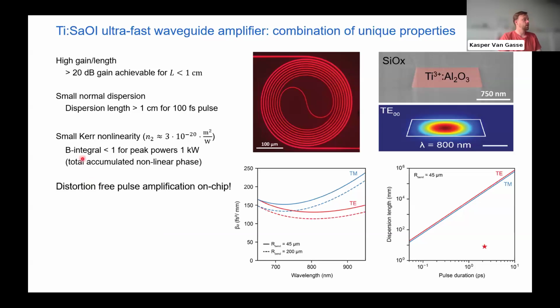On top of that, because of the small Kerr nonlinearity and the fact that it's also short, we have almost no nonlinear spectral broadening or phase accumulation of our pulse. And that's all the way for peak powers up to 1 kilowatt. So you have to imagine it's a very tiny cross-section. You can go all the way to 1 kilowatt. That's starting to be on the order of 100 gigawatt per centimeter squared. So very high intensity. That means that with this simple system, we can really do distortion-free pulse amplification on chip. And that was not really achieved before.